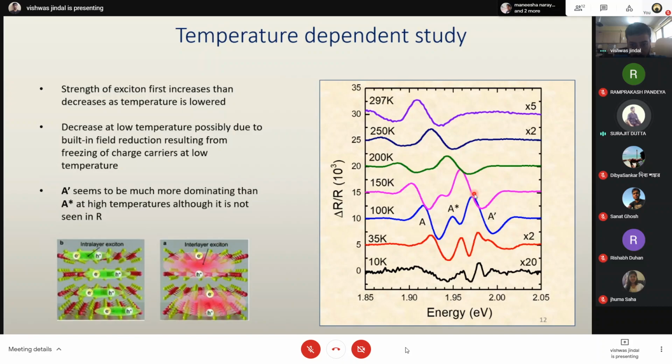So one is the thermal broadening because of temperature, and the other thing is how good your sample is. There is some inhomogeneous broadening related to defects. If you had a perfect sample which is free of all defects, no doping, nothing, then the broadening would be related to the lifetime of your exciton. You remember that delta E delta T? That would be your ideal.